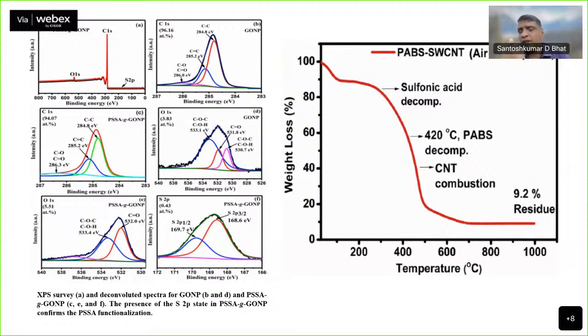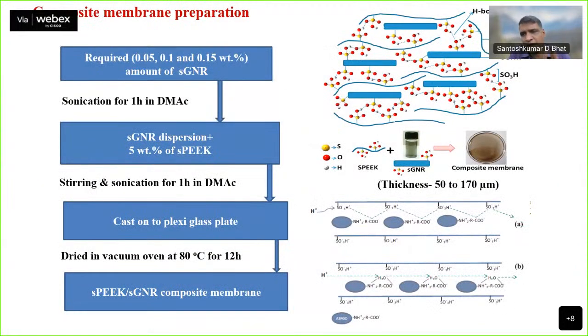And also when we see the S2p peak, we can qualitatively convey that S2p peaks are there. So XPS can qualitatively convey that the carbon material is ready for addition to the polymer matrix. So when we do this, then you can form a membrane, and the membrane formation is again simple.